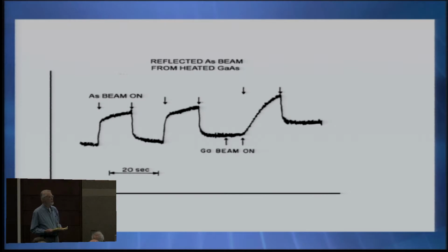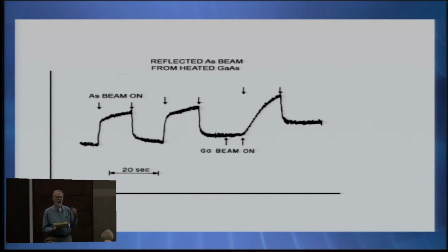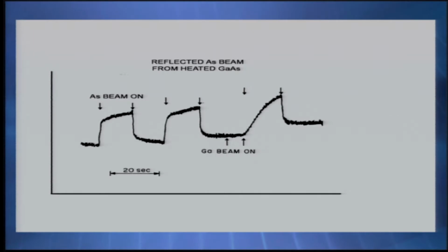So we've got basically square pulses. But when there was a little bit of gallium on the surface, it behaved totally differently, and you can see that there is now an uptake of arsenic. It's not bouncing off the surface when there's gallium present. So this suggested that here is a way to make stoichiometric compound films. People had done a lot of work trying to evaporate compound semiconductors prior to this. They did such things as putting a gallium arsenide source in a tube and heating it up, and then figuring out that somewhere along the length of this tube, the atoms would be arriving at the surface to make a stoichiometric film. Well, what this showed was that you didn't need to worry about that. You could make a stoichiometric film just from these molecular beams. And this was a pretty convenient way to do it.